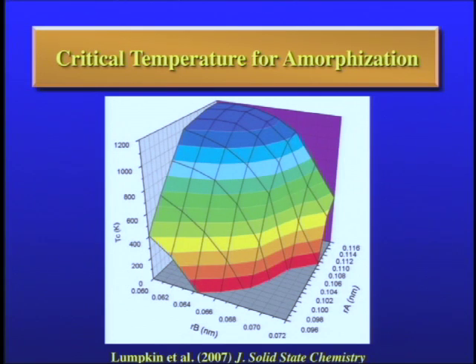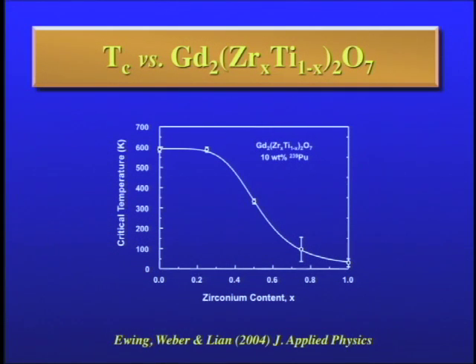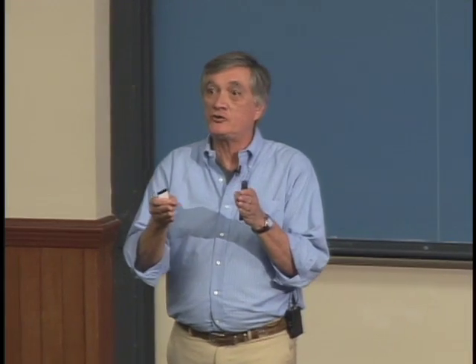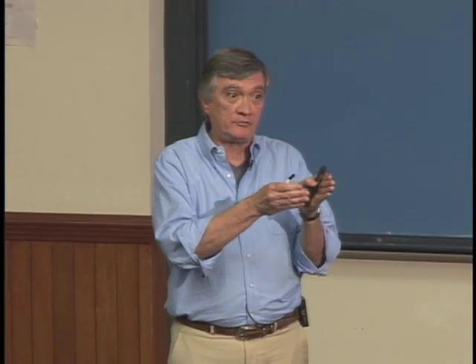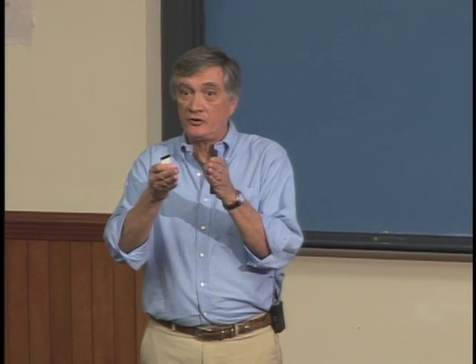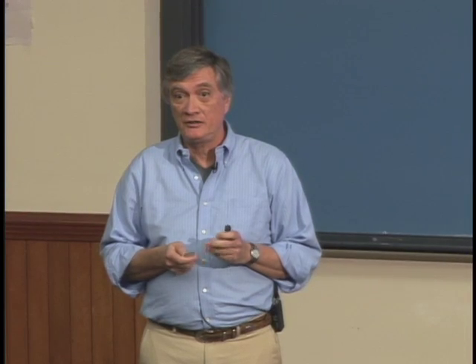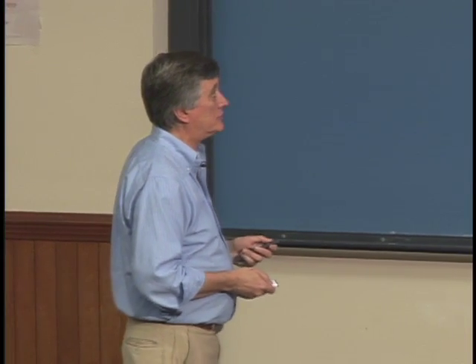And what this means is, let's say gadolinium titanate, so you have the radius of gadolinium, and then you substitute zirconium, that will be just a cut through this curve, and it will look something like this, right? So if we just take that binary as an example of what we might do, and I have to say now, we'll have models for damage accumulation, damage annealing, which are based on all the data from natural samples, from the ion beam experiments, and from the plutonium and curium doping experiments. It really was a fair amount of work, but the result is simple.